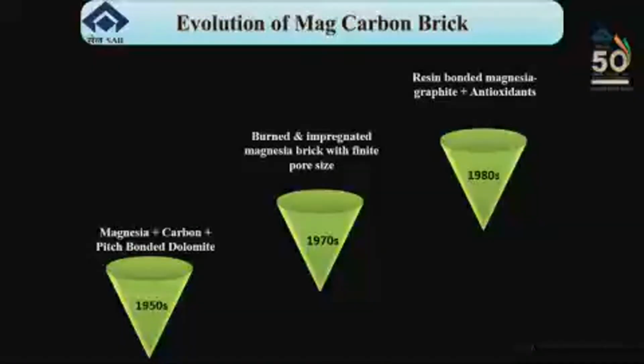The evolution and use of magnesia refractories in combination with carbon started in the early 1950s with magnesite fraction bonded with pitch. In the 1970s, the burnt and impregnated magnesia brick with fine pore size became the standard for the charge pad and the other high wear areas, starting the beginning of the zone lining for basic oxygen furnaces.